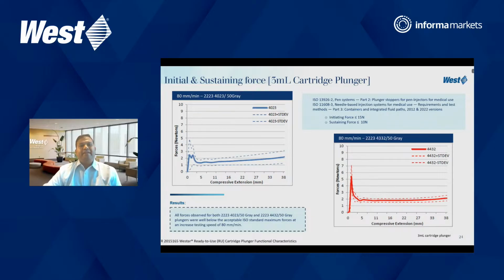Starting with the 80 millimeter per minute data, on the left side you can clearly see the data for 4023, which is the bromobutyl formulation, and on the right side in red is the chlorobutyl option. What you can clearly see on both options is that the break loose force is hovering around 2 to 3 Newton for bromobutyl, while it is 5 to 6 for chlorobutyl formulations, which is well within the 15 Newton limit for initiating force. For the sustaining or gliding force, it is hovering around 2 to 3 in both cases. So it is a consistent gliding force and break loose force for both cases, whether chlorobutyl or bromobutyl formulations, well within the limit of ISO standards.